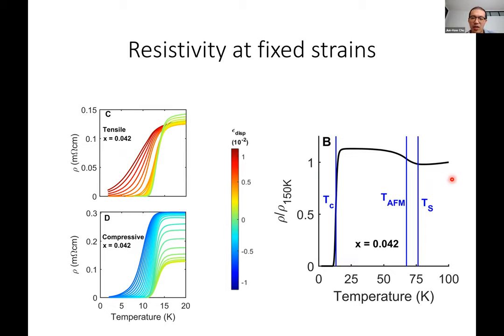Yeah, but there's a caveat, which is we determine TN from R versus T in the fixed strain curve, and to be honest, I'm not that confident in really determining it. In the zero strain state, this peak is really sharp, and the anomaly in the resistance derivative dR/dT versus temperature looks just like the heat capacity. But as you apply more and more strain, the TS anomaly has obviously broadened and smeared out. Although we're still observing a peak, it's becoming more and more questionable to use that peak to identify TN. So if we can, for example, combine with your neutron experiment, that would be great to quantitatively map out this phase diagram.